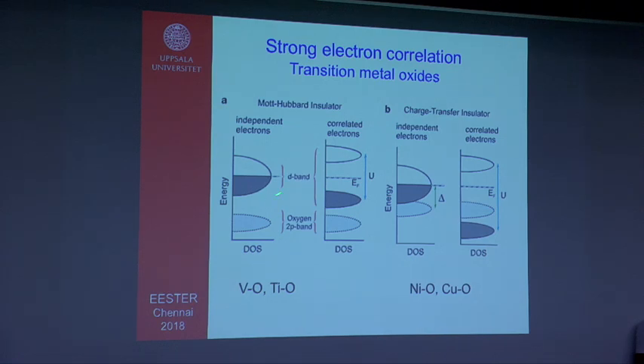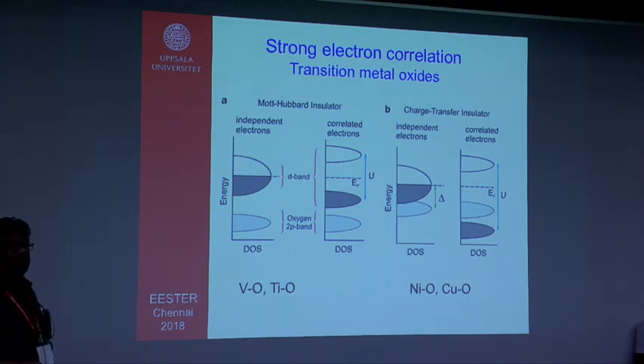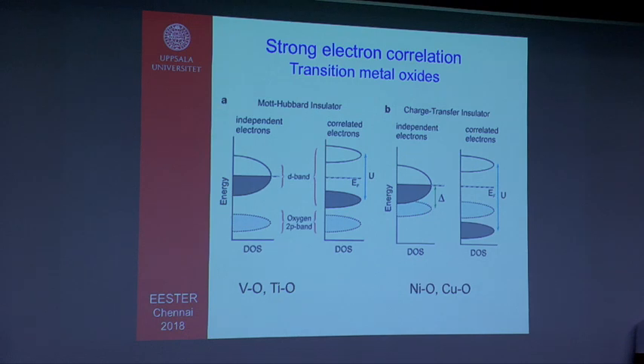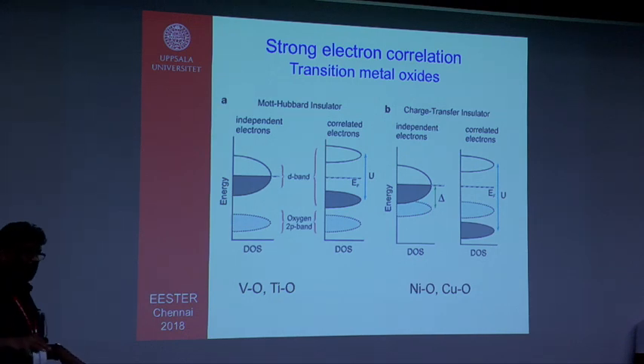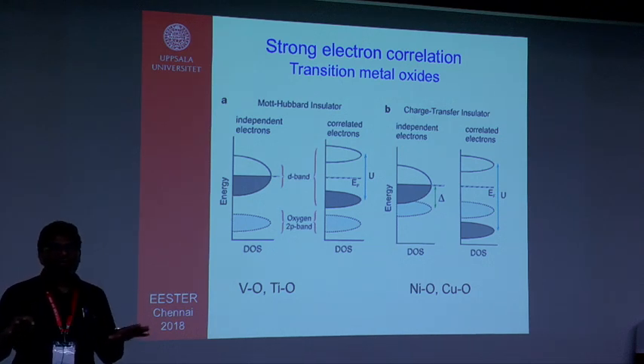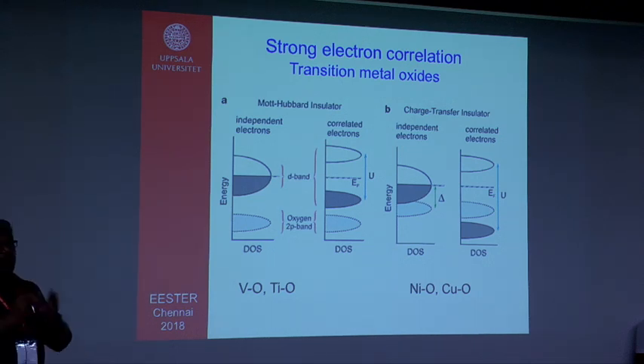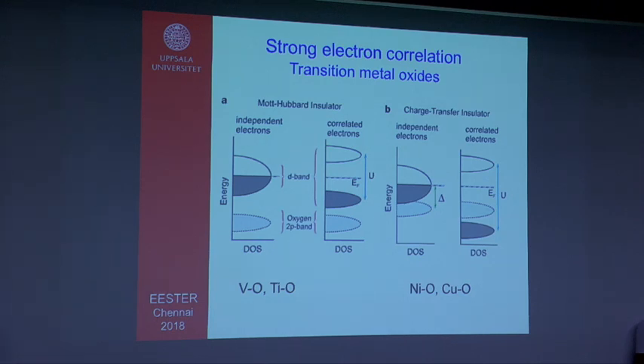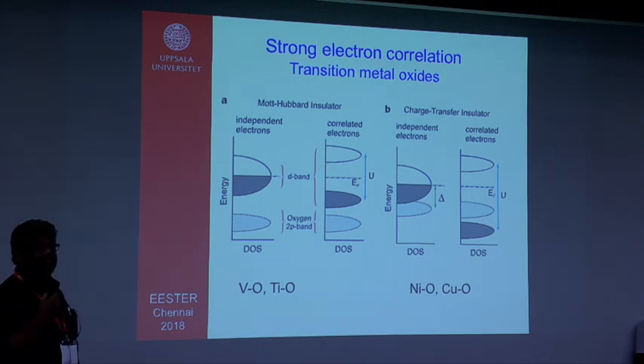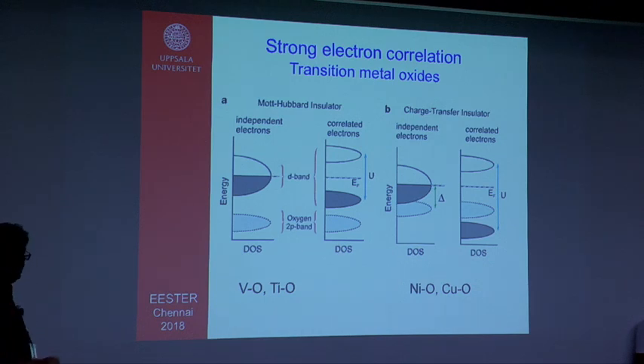So what happens is that when we do the approximation of LDA or GGA, the exchange correlation functional is very much approximated to a uniform electron gas, homogeneous electron gas, where this homogeneous electron gas cannot take into account the localized nature of the electrons. And there this theory fails, and it fails to give us the correct electronic structure of the insulating character of the system. It gives us a metallic structure, which is wrong.